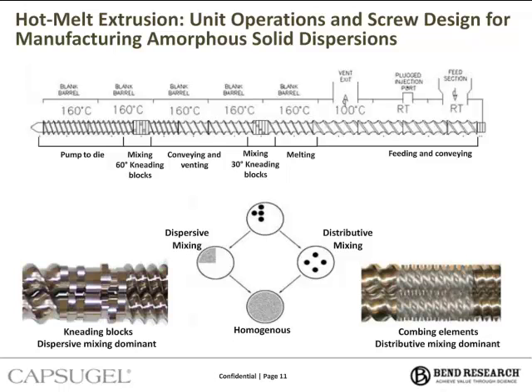Now, generally for HME, we will do distributive mixing followed by dispersive mixing, and if we look at the screw design, we can see this. In the first mixing section of the screw, there's 30-degree kneading blocks, so that's a lot of distributive mixing and a little dispersive mixing. And then later on in the screw, we have 60-degree kneading blocks, which is a lot more dispersive mixing and a lot less distributive mixing. Now, for a fixed screw design, the mixing intensity is a function of residence time, specifically the span of the residence time, and screw speed. So faster screw speed is better mixing.